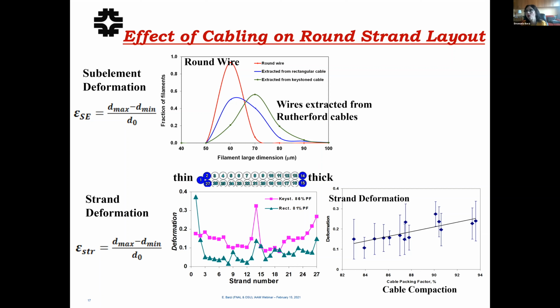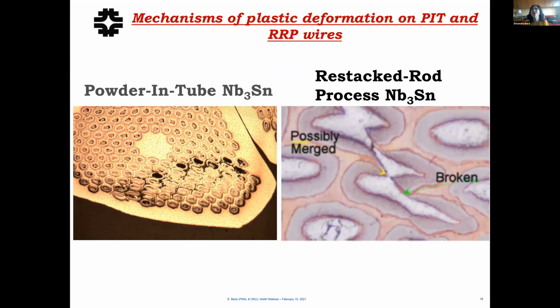So you have a lot of parameters in this business. And I'm not even talking of the magnet here, just I'm at the cable stage now, at the Rutherford cable stage. So for instance, what happened is that when looking at the optical images and SEM images and microstructure, but this, I think this was done just with an optical microscope. Here you can see the thin niobium element that I showed before in this restacked rod process, niobium-3 tin wire that we ended up using. You can see how they deform in the cable, and you can see how they merge.